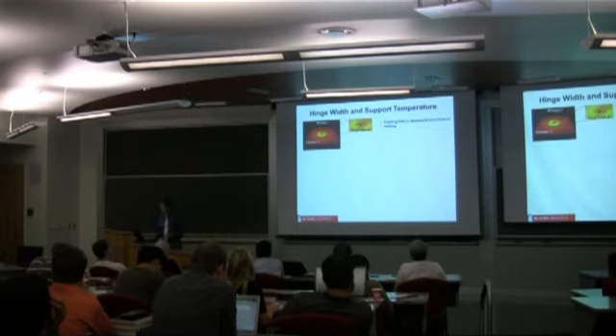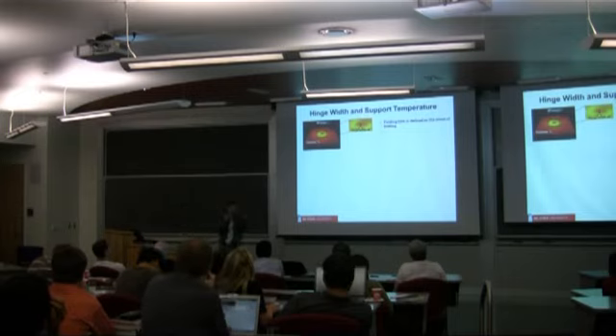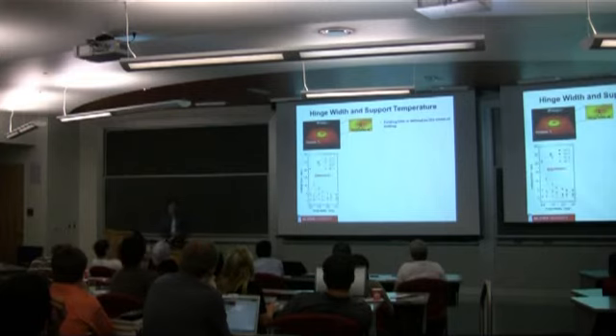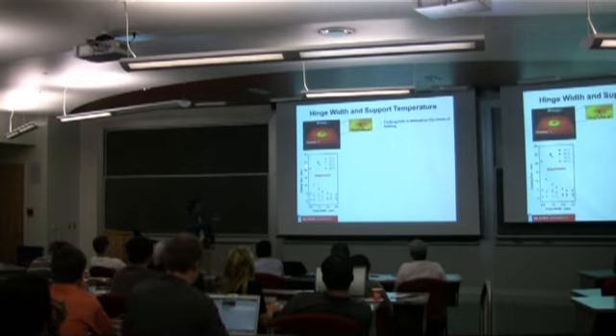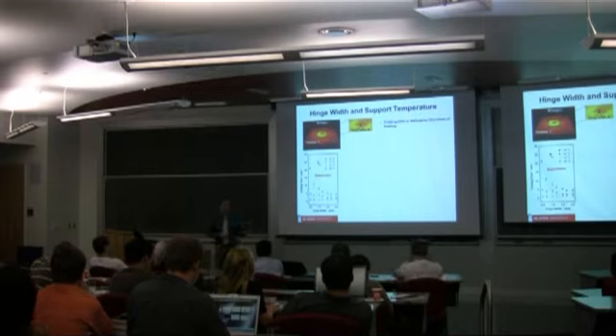Okay, so we did a bunch of measurements, and we sat there literally with a stopwatch and with our eyes, and we watched these things as they started to fold. And we measured the amount of time for it to go from here to just starting to move. We call that the onset of folding. And we showed this experimentally here in this plot, in which we vary two things, the hinge width, and what you see in this data is that the folding time decreases as the hinge width gets wider. And that should be sort of intuitive. The wider it is, the more energy you're delivering to the hinge, and the easier it is to fold.